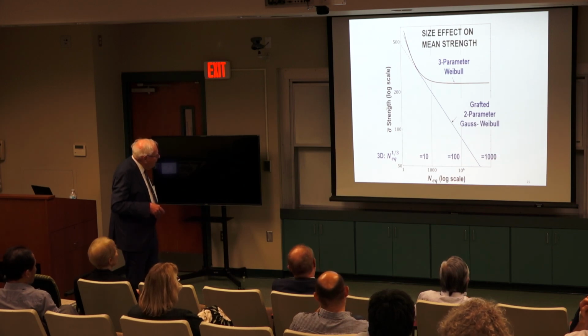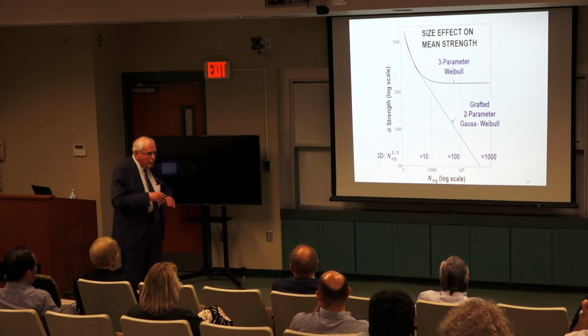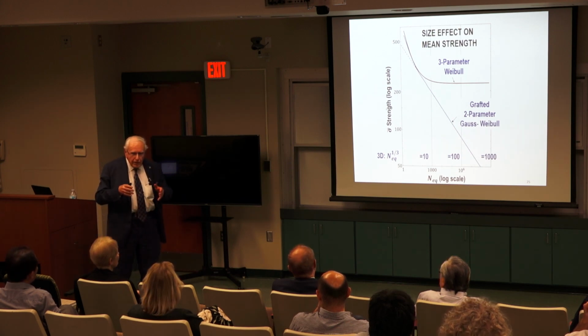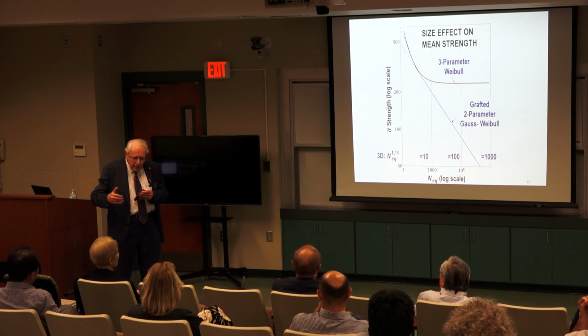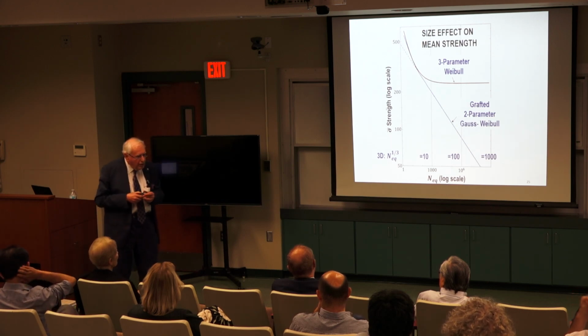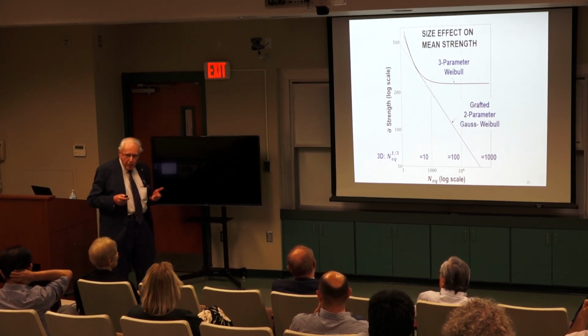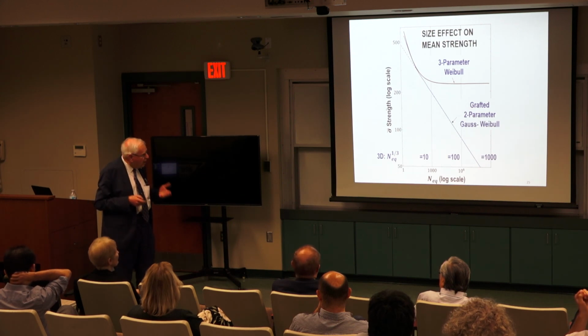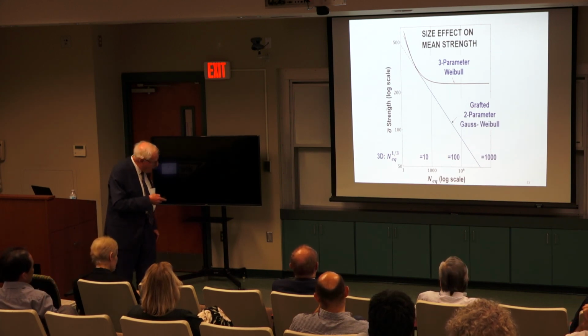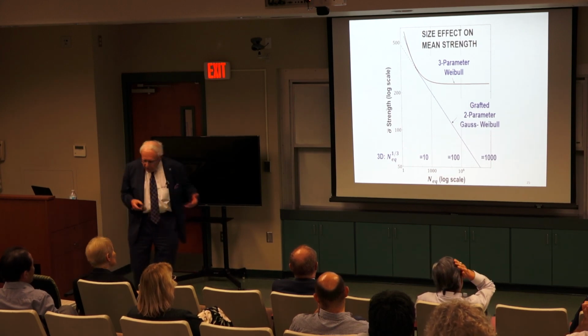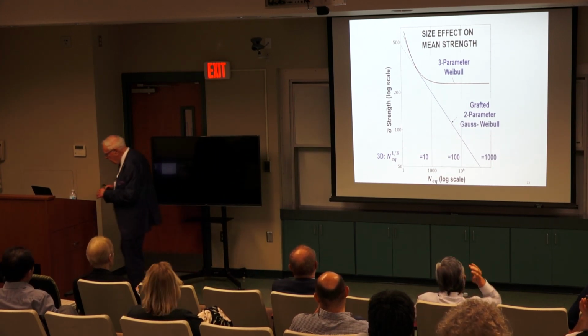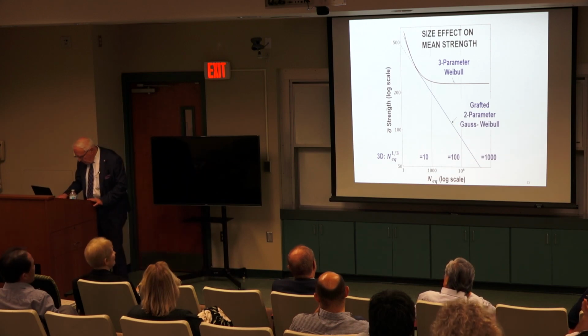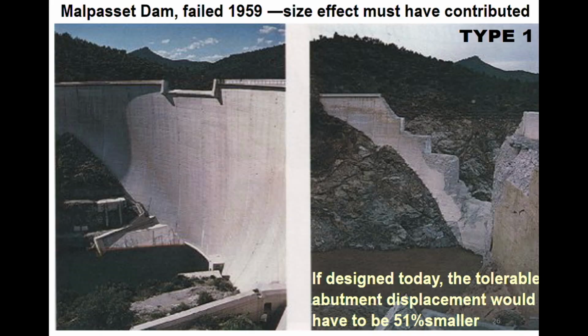That's actually 1 billion RVEs. But under uniaxial tension, a prism would be what? 1000 RVEs this way, 1000 this way, and also the other way. If the RVE is 1 millimeter or 1 micrometer, you easily realize it. With a positive geometry, the structure becomes unstable after the failure of 1 RVE. That's what's happening, and this is the error. So, this has been published already almost 10 years ago, but there is no response in the ceramics community to this.